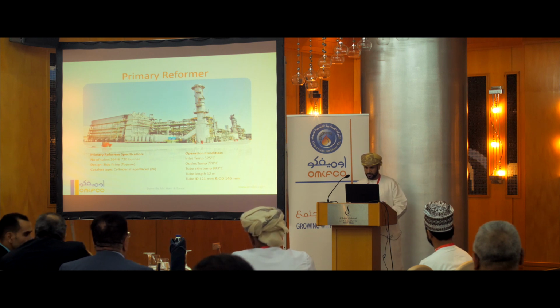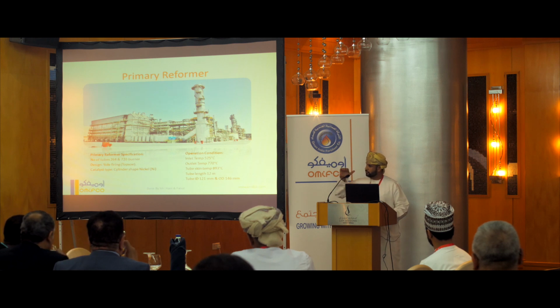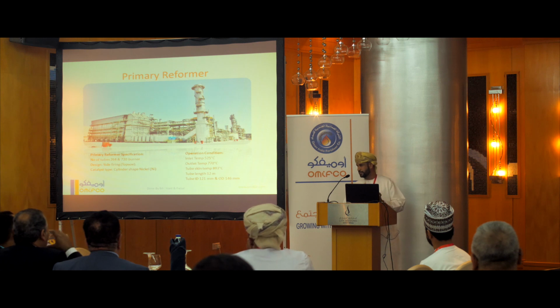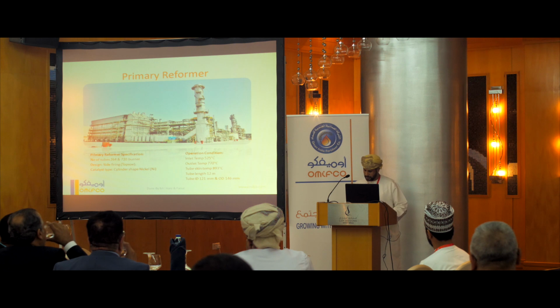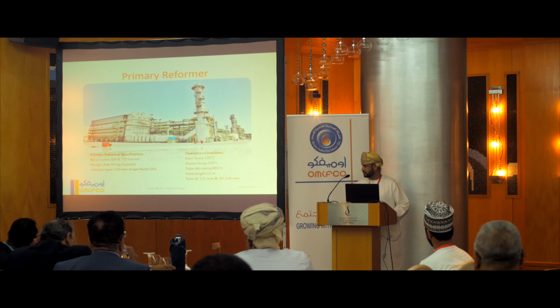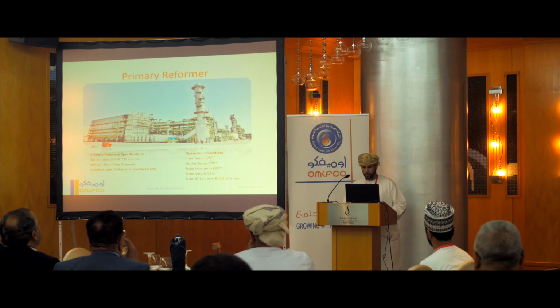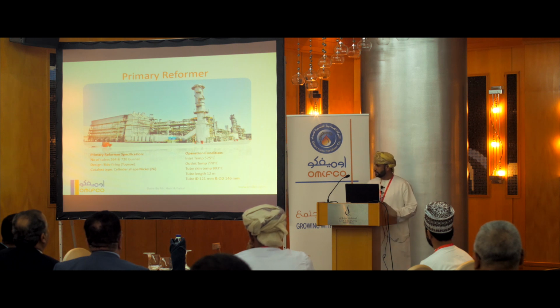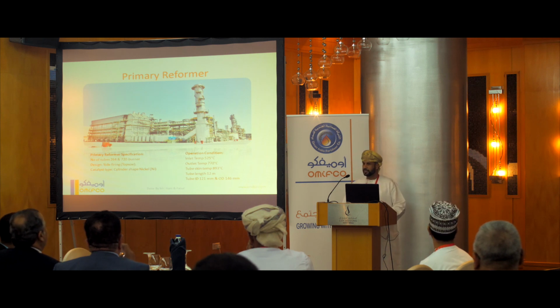The inlet temperature is 525 degrees from the first coil, from the flue gas outlet of the reformer. The first coil is around 525 with the steam and gas mix feed to the primary reformer top tubes. And the outlet temperature is 770 degrees centigrade. Tube skin temperature design is around 893 degrees centigrade, but we are working at somewhat less than that, and we don't face any problem till now with any tubes.